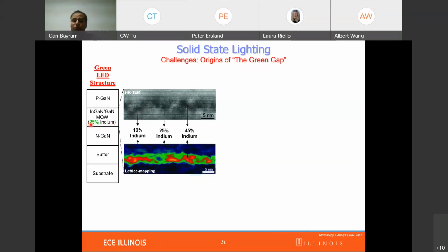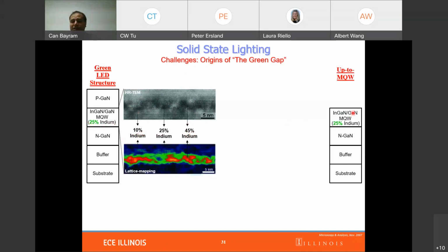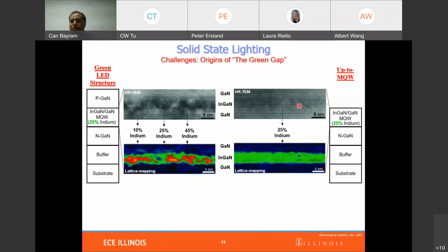So the average indium content is 25%, but you have indium-rich regions with 45% and indium-poor regions with 10%. Now, if we grow these structures without the capping, without the p-GaN layer, we see that indeed our indium is uniform as grown. So what's the problem?